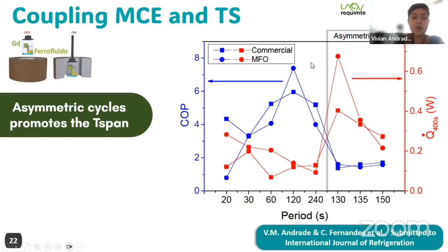And here we have the coefficient of performance close to the theoretical one in the symmetric cycles. Although it seems small, we also have a small device, it's this size. For the temperature that we were at, around 30 Celsius degrees, it's a good temperature span. It seems small, I know, but it's close to the theoretical one. And this is a proof of concept.